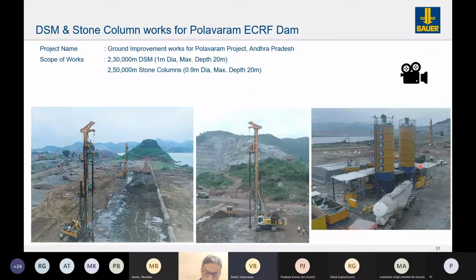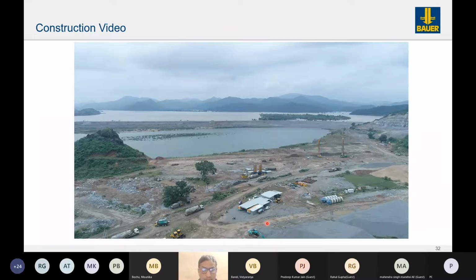So this gives you an overview from the top of how it has been set up. This is the plastic concrete cutoff wall where we are installing the columns, and the batching plant, which is catering to the requirements of the cement slurry required for the injection. We are pumping close to 330 kg of cement per cubic meter of soil that has been improved. I'll just quickly show you the video of this particular site also.